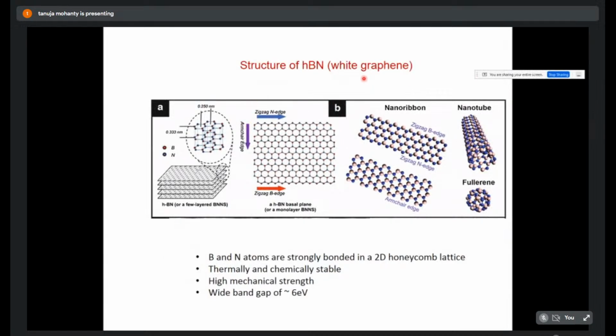And then I can say about the structure of HBN. HBN is hexagonal boron nitride. We have seen graphene, but this is called white graphene. Graphene, we say, is a honeycomb lattice having the hexagonal bond structure, and they have layers. But here, in the case of hexagonal boron nitride, you have boron as well as nitrogen. The difference is that graphene has a zero band gap, whereas hexagonal boron nitride has a band gap of 6 eV. For TMDC 2D materials, I was saying it is between 1 eV and 2 eV. In graphene it is 0 eV, and these materials have a band gap of 5 to 6 eV. Now, a 5 to 6 eV band gap is very high. It can be considered an insulator.